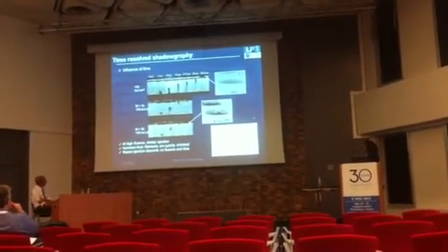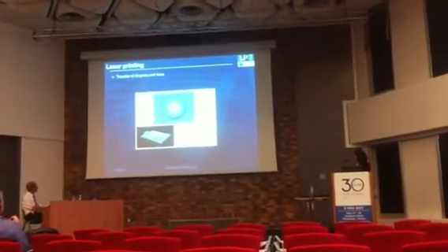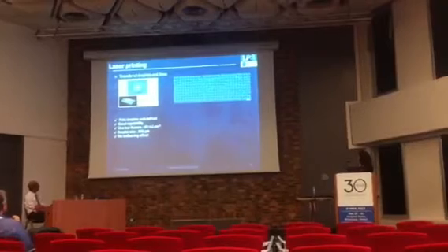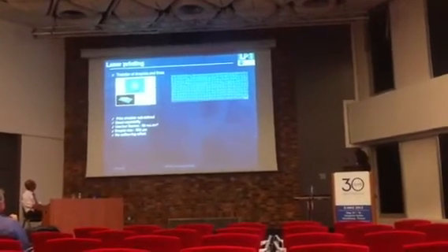So now we print this kind of pixel, and we apply this characteristic for transfer droplet and line for our application. So we can print very well-defined droplets with a very smooth profile. With these droplets, we can print a matrix to perform repeatability. We can see that it's very reproducible and with a well-defined deposit.